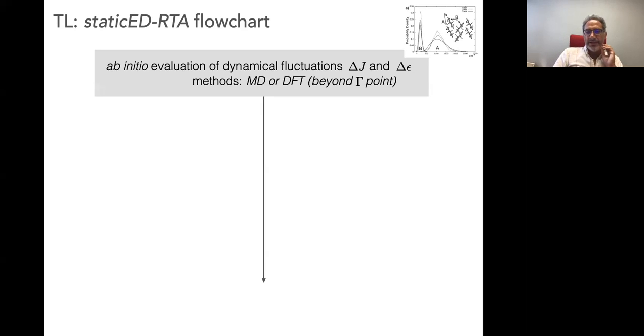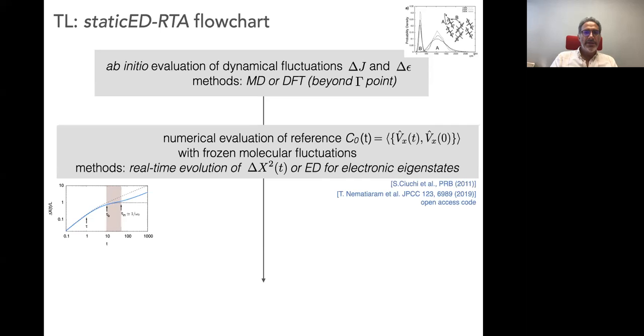So there is maybe some ambiguity in what is transient localization theory. What I mean here by transient localization theory is just a specific flavor where we solve the simple problem with static molecular displacements, and then we apply this relaxation time approximation to mimic the dynamics. So basically, if you want to analyze a material like this, you need to evaluate by some ab initio method the fluctuations of the transfer integrals and the fluctuations of the site energies. Then you solve your problem for frozen displacements, like frozen molecules.